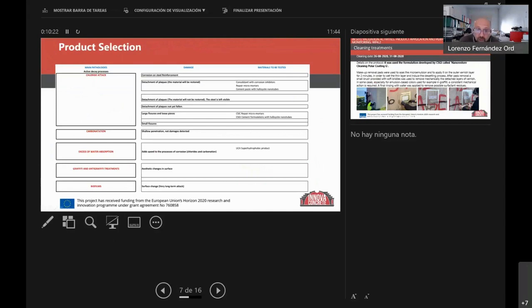So here you see, on the left, the main pathologies we found, which are this chloride attack, the carbonation in very shallow areas. There is excess of water in all the sculpture, and this is because the sculpture has a lot of porosity. We have also problems with graffiti and the cleaning of the graffiti. The town hall has been cleaning the graffiti, and we have problems with that because the cleaning of the graffiti has taken the surface of the sculpture, which is very special, and also because of the constant water, we have biofilms on the surface of the sculpture.